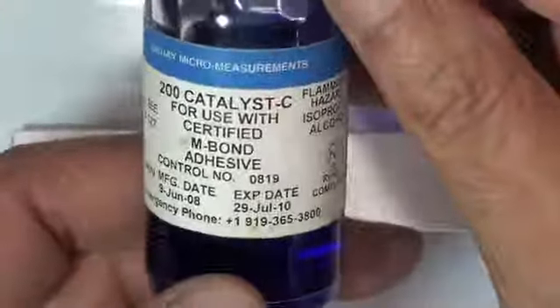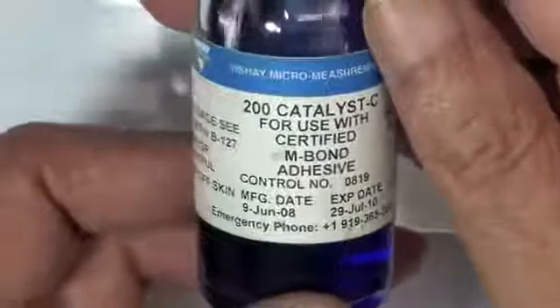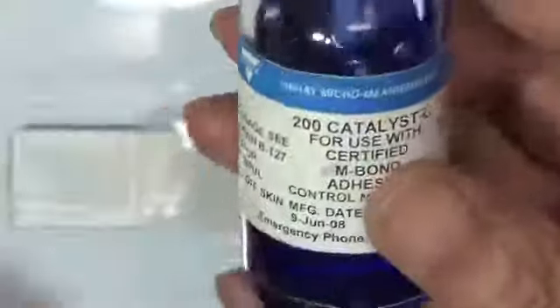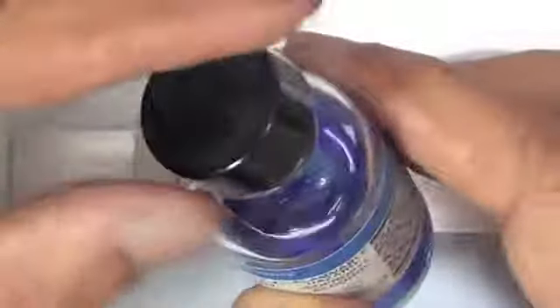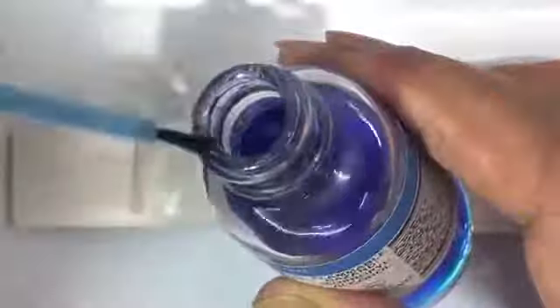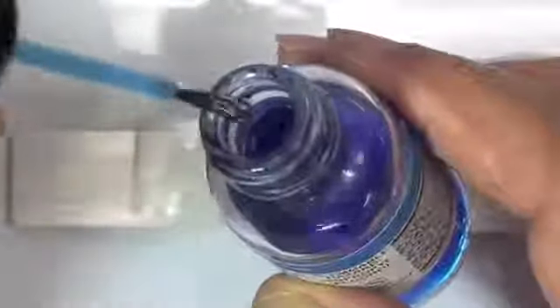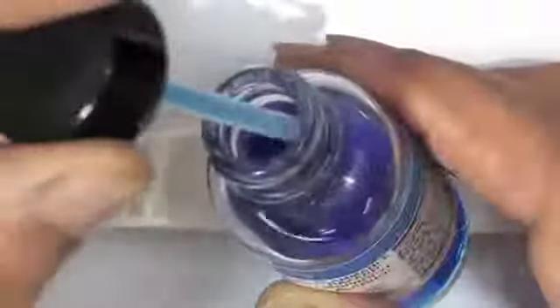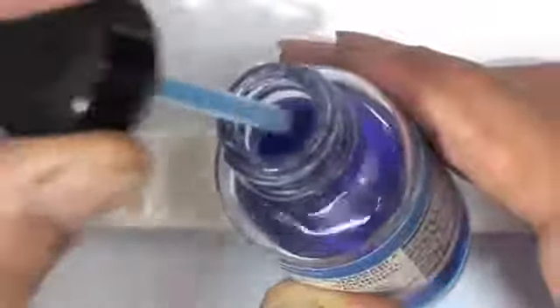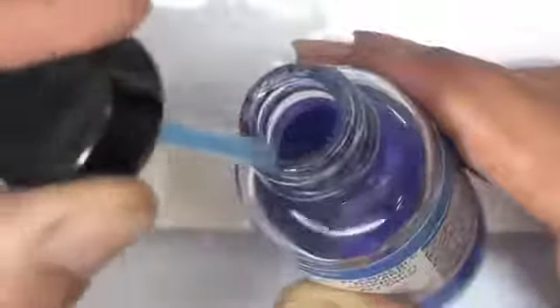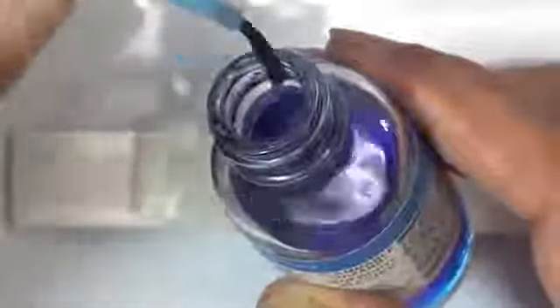Now, the material that we're using here is M-Bond 200 adhesive. This is sold as a kit that contains this bottle of catalyst and a bottle of the adhesive. The purpose of the catalyst is to speed up the chemical reaction and allow the adhesive to cure a little bit faster. It requires very, very little catalyst. So he's going to wipe that brush off several times on the inside of that lid. We just want enough catalyst to wet the surface. We don't want to have any liquid that stands on the surface.